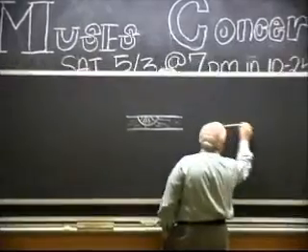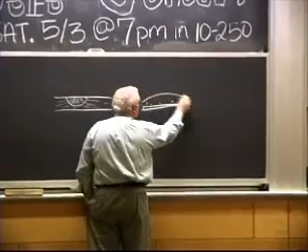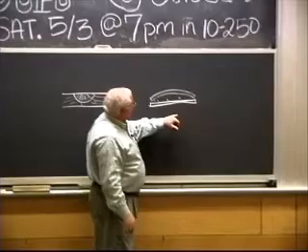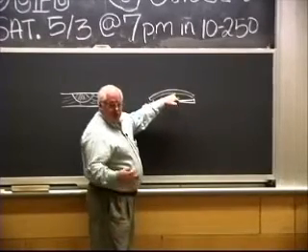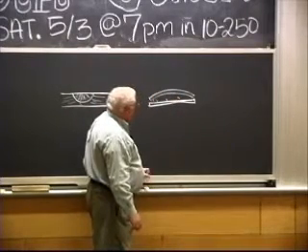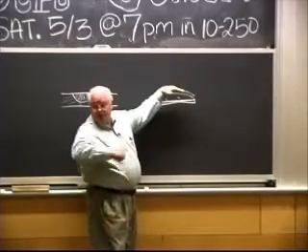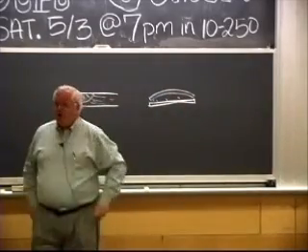And you develop what's called an Almen gauge for this. This is the standard. You take a piece of steel that's flat, and you peen the surface, and after you peen the surface, the thing will bow up, because whatever stress you induce in it while you're working it, it'll go in the opposite direction when you're all done. By compressing the surface, you expand the surface, and so when you're all finished beating on it, it will bow up. And you measure the height of that bow, and it tells you how intense your peening is.